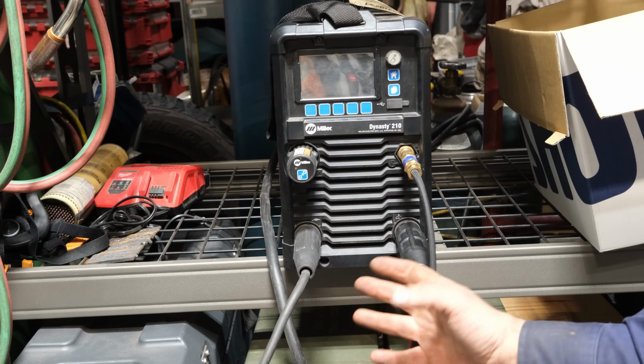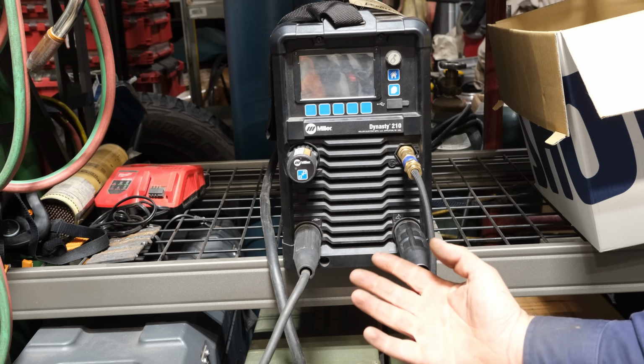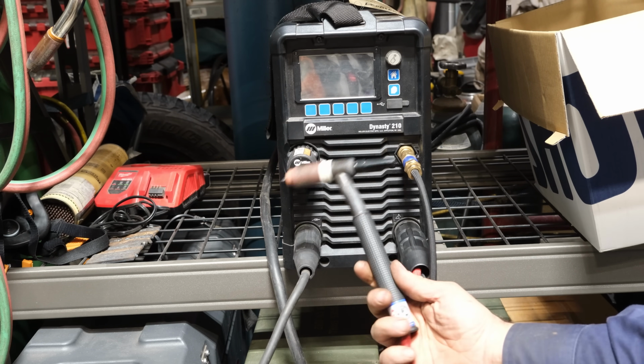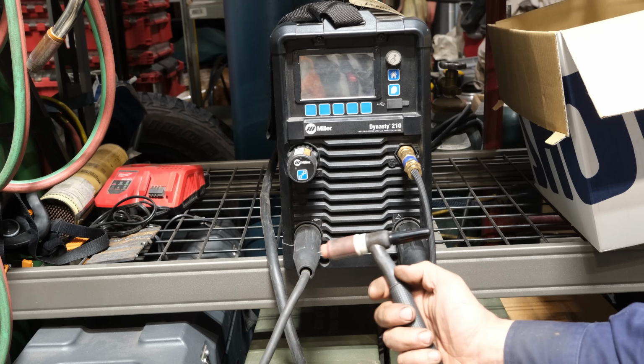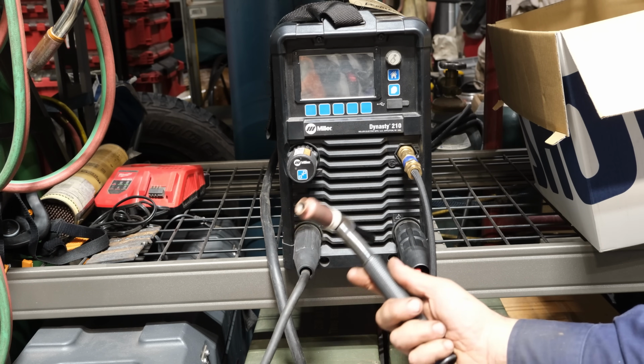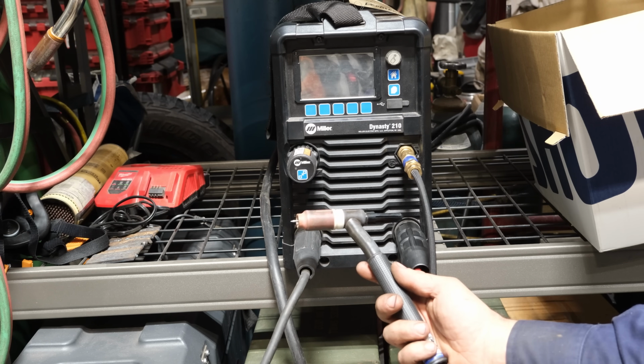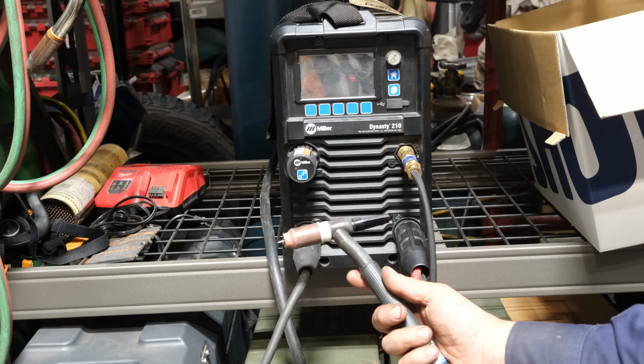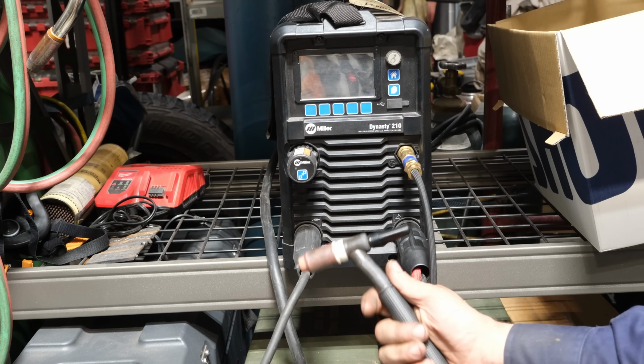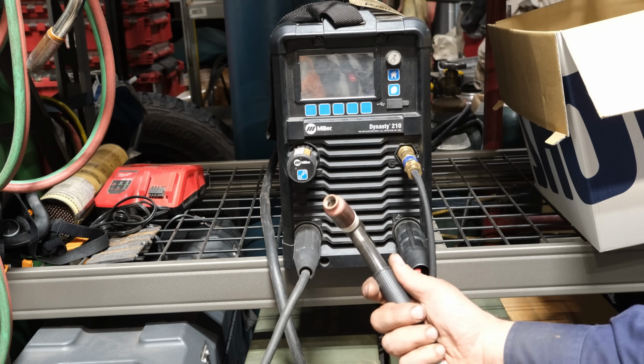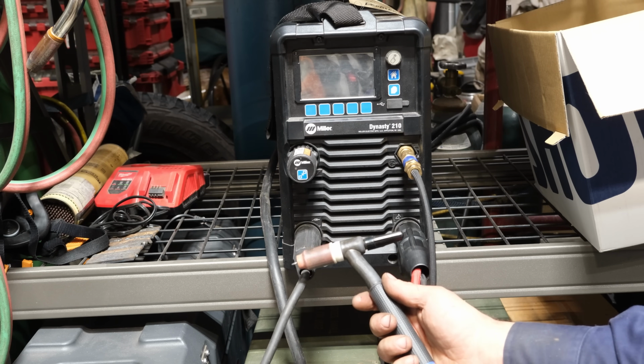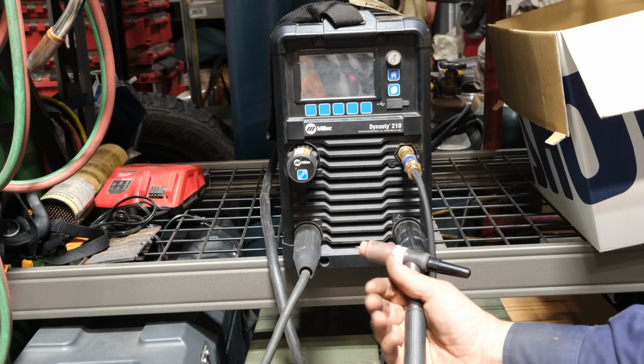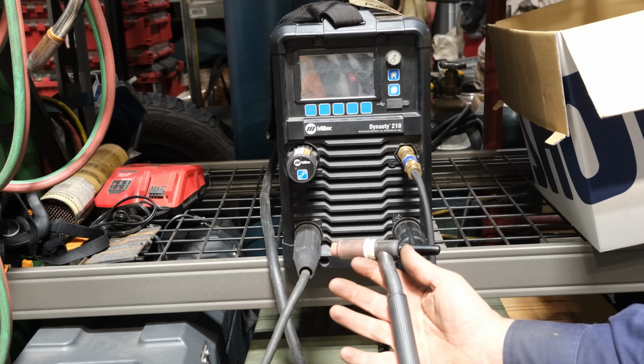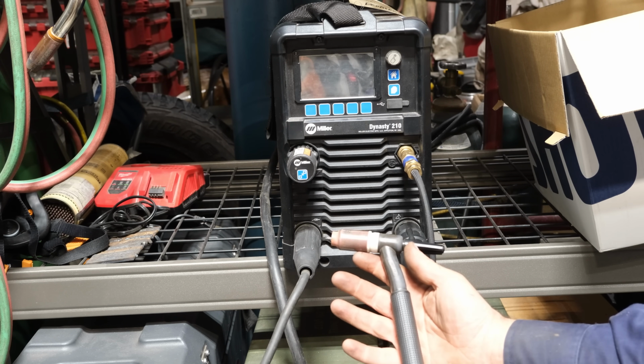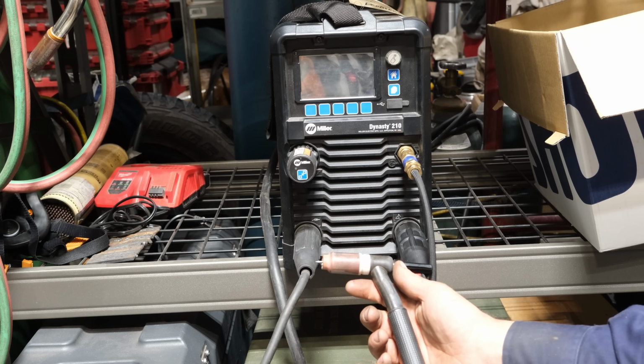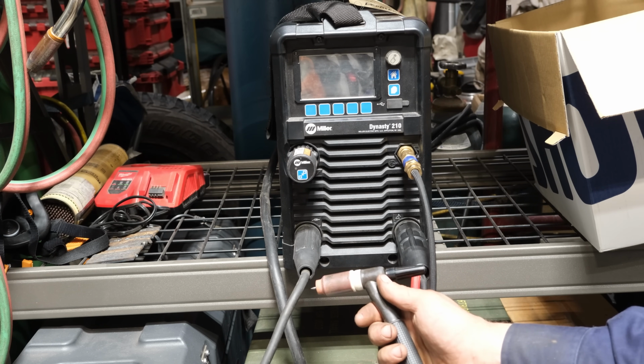Now, there is a caveat to this. If you weld on AC TIG for aluminum, this torch will barely be able to handle 150 amps on AC before it starts literally smoking. And that is where water coolers become more of a necessity, with the AC end of things, because the heat input into the torch via the tungsten is so high that you really need some method to cool it down, and air cooling starts to become inadequate. So if you have ambitions on doing a lot of aluminum welding that's thicker than 1/8 inch, you're going to end up at some point buying a water cooler. So that is something you should be keeping in the back of your mind.